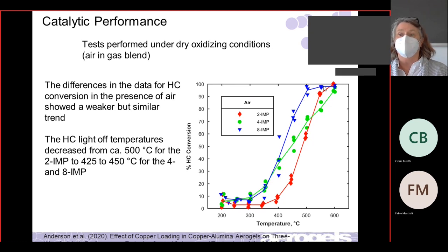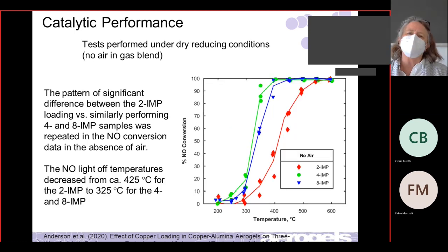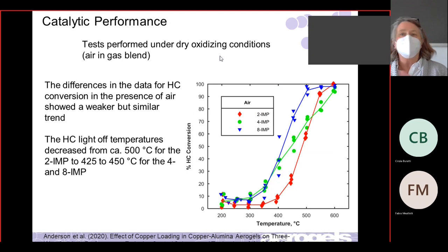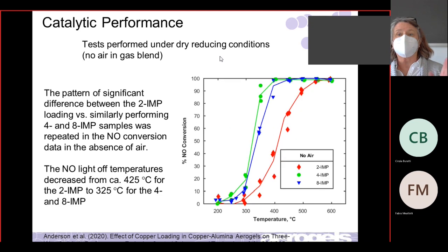So that was okay. The next one is the NO. If I test the NO in an oxidizing condition, it does nothing. It won't go away because there's too much oxygen around. And this is why they do fuel lean, fuel rich, fuel lean, fuel rich. Because if you have a reducing condition where there's not very much oxygen, then you can convert the NO. And so this is the NO conversion versus temperature again, and we're looking for the 50%. The light off temperature decreases significantly when I go from 2 to 4, right? From 400 to 3-something. So, these are okay results. The CO results are really promising. The other ones aren't as promising.